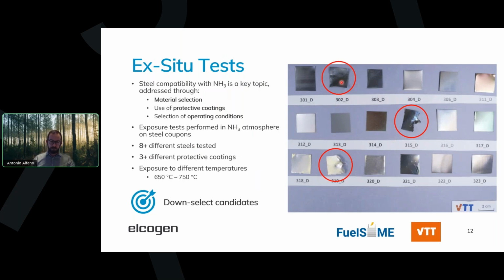You do still have candidates which essentially are destroyed at the end of the test. Others are looking pretty good, but this also shows that this is already a good screening to down select some of the candidates which are suitable for operation with ammonia.